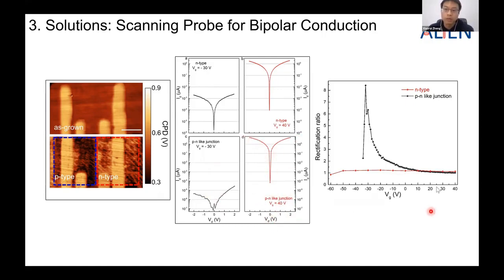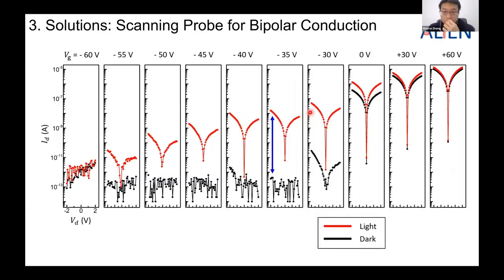Okay, this is another proof of the tip-induced p-n junction doping. Because the p-n junction has another unique, interesting property, which is the photocurrent. So we also demonstrated the photocurrent at different backgating. As you can see, still at very small backgating conditions, like -35 volts, we can get a huge difference between light current and dark current. The ratio is as large as around four orders of magnitude.